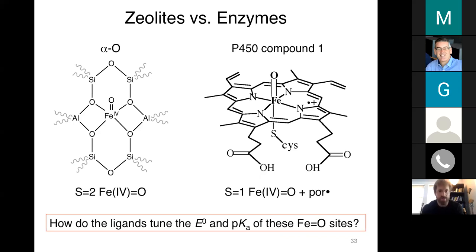So I'll just recap a little bit about what we've said about alpha oxygen here. In this case, we're going to think about how the ligands tune the reduction potential and pKa's of these iron oxo sites. And what I've told you is that the weak donation of the zeolite lattice into this iron oxo core of alpha oxygen results in a high spin electronic structure, and this leads to a very favorable reduction potential, which facilitates H atom abstraction from hydrocarbon substrates. So in this case, the favorable reduction potential of the iron oxo core drives reactivity.